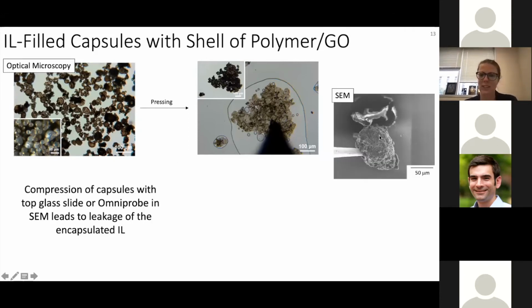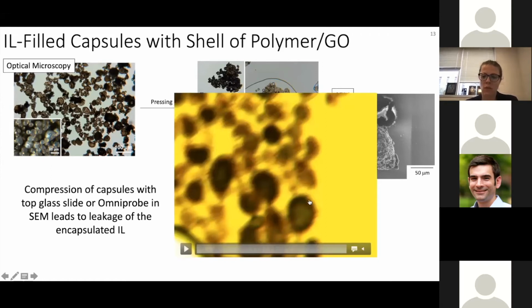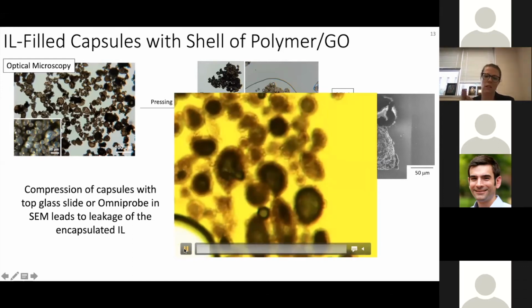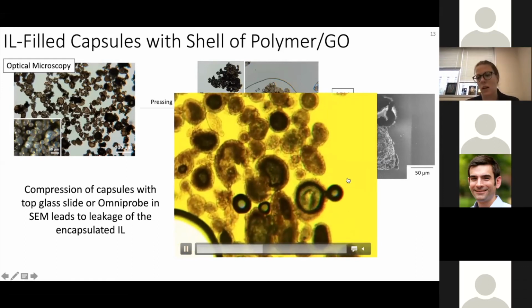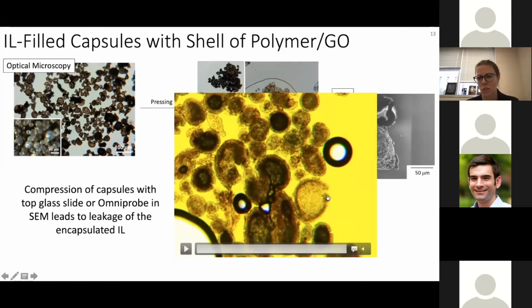Case Western let us do this in the SEM where we actually poked it and the ionic liquid came out. And then we can watch this in real time. So here the capsules are in octane. And so this is a good one to watch where we press the sample on top and we see the ionic liquid is expelled from the capsule. And we do see a rupture here.